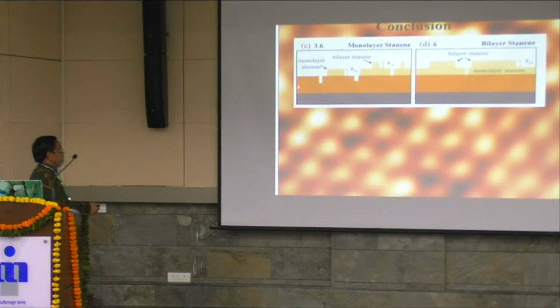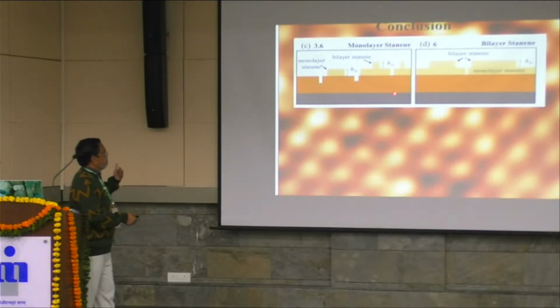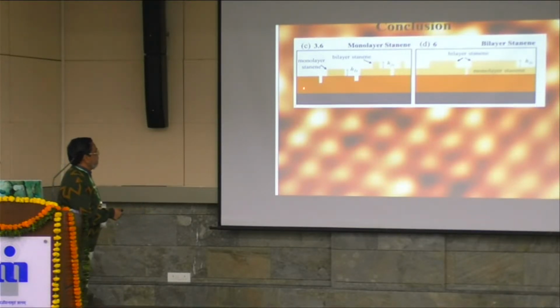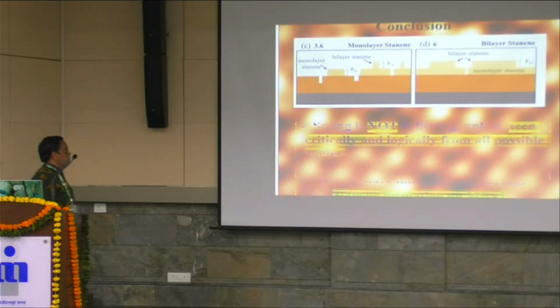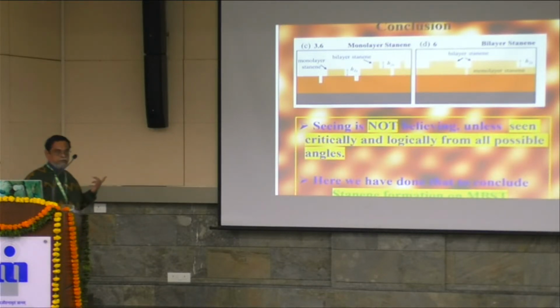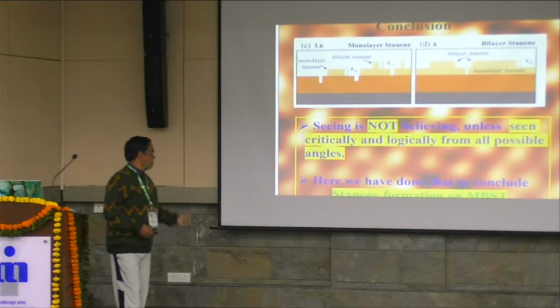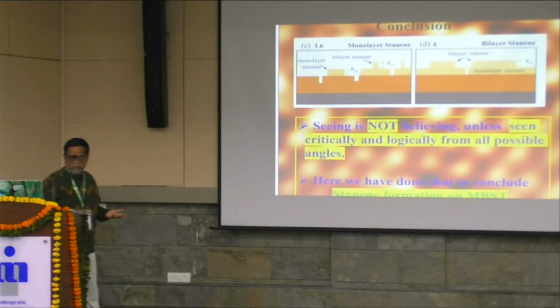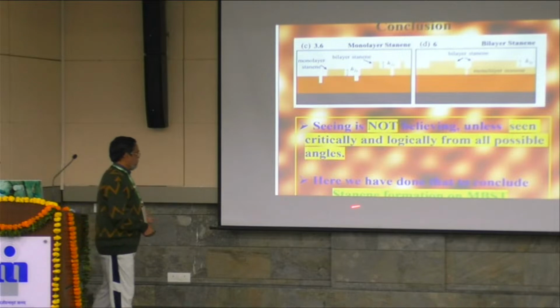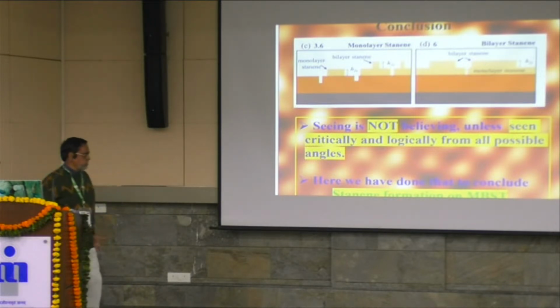So this is the cartoon figure which says that this is the buffer layer formed because when tin reacts with the tellurium on the surface of the MBT, after it has reacted, then it starts forming stanene. So these are the monolayer stanene, and then there is the bilayer stanene position on that. So to conclude, seeing is not believing unless seeing critically and logically from all possible angles. So this is the message, and here we have done that to conclude the stanene formation happens on MBT. Thank you.